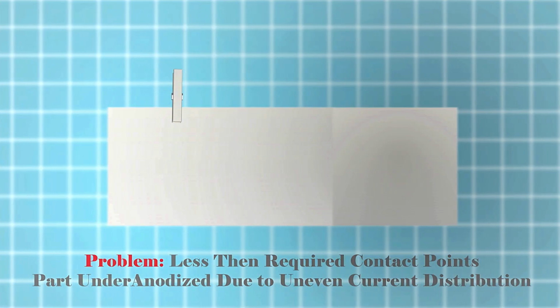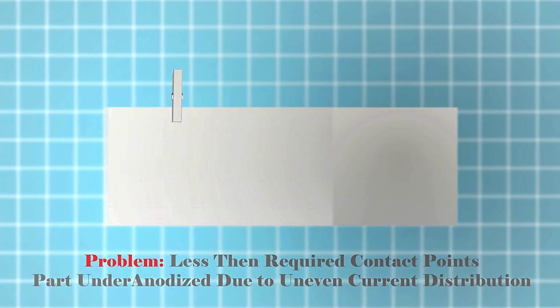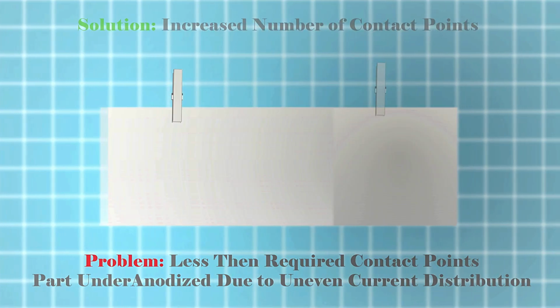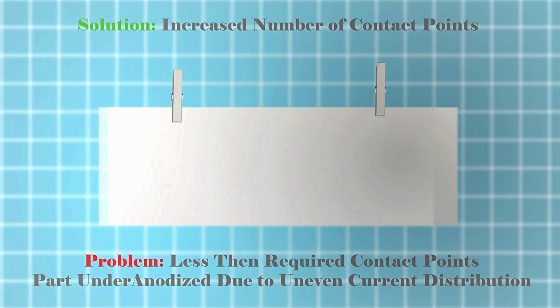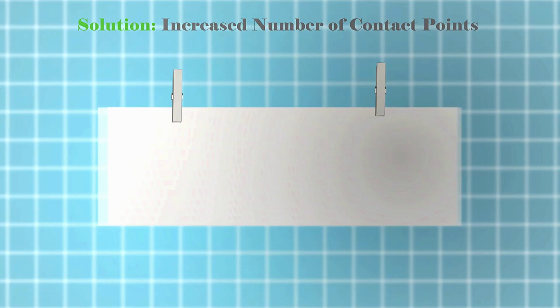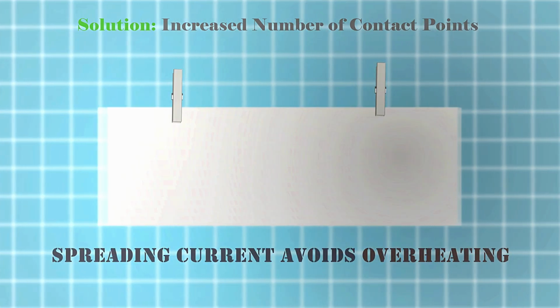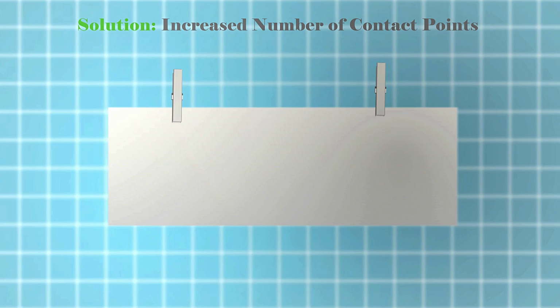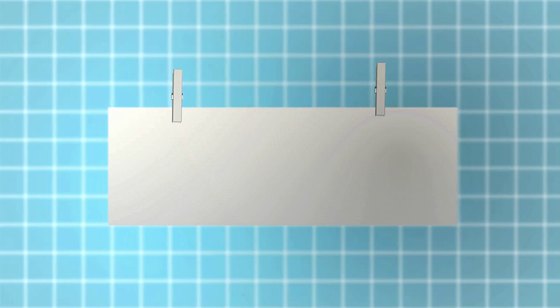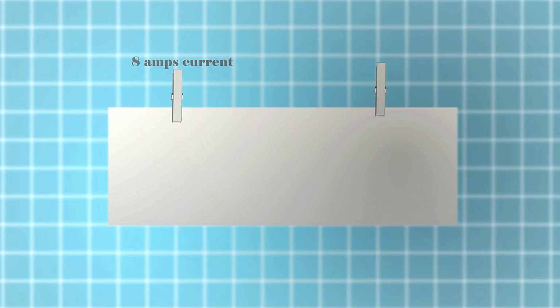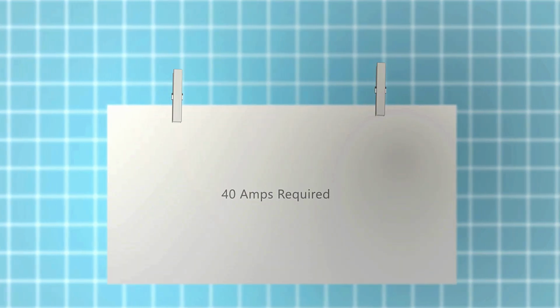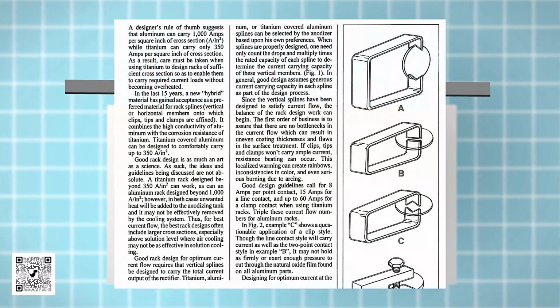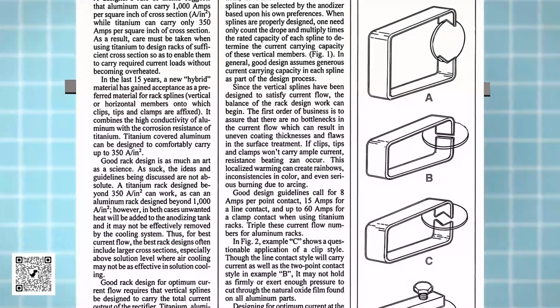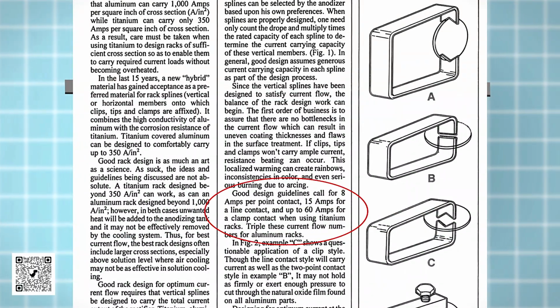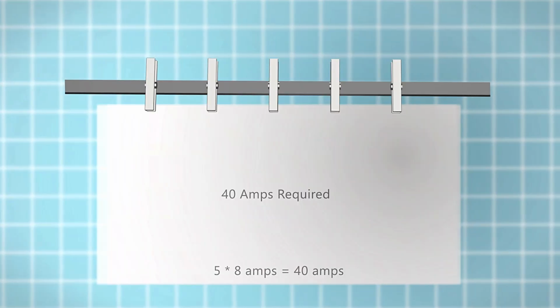Think of a long part. If you only attach it at one end, the far end might under-anodize because the current path is longer. Multiple contacts act like parallel wiring, delivering current evenly across a big part. Plus, spreading out the load avoids overheating any single contact. As a rule of thumb, each titanium contact point comfortably carries 8 amps before you risk heating. Big parts requiring, say, 40 amps total should have 5 points or use beefier clamps. It's like using multiple smaller engines to pull a heavy train, rather than one engine straining to do it all.